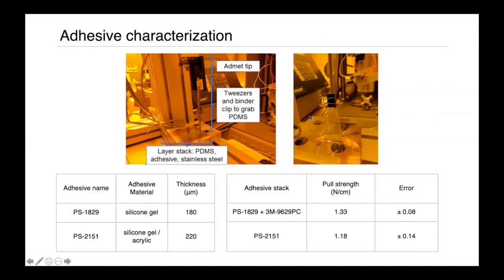Because the adhesive strength is important for durability and device uniformity, pull-off strength adhesive testing was performed to determine the adhesive strength of various adhesives to PDMS as well as the stainless steel stylet.